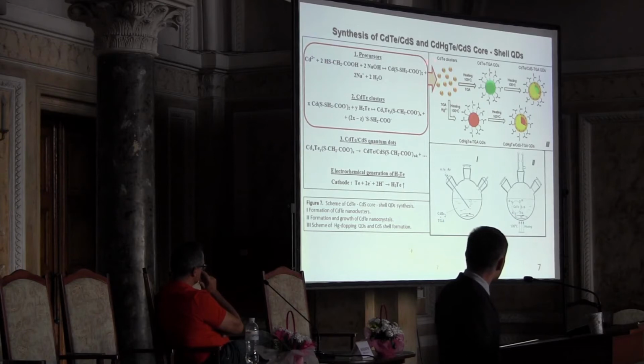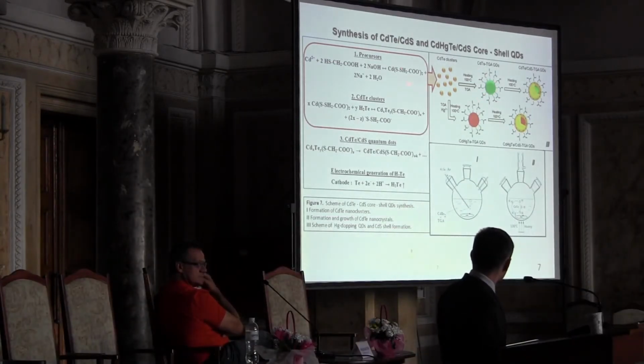And afterwards you get those clusters, and to grow particles out of them, you heat it up, either for short terms, then you get pure cadmium telluride particles. If you do it longer, then partially those thiols start to decompose, and you can basically end up with a core-shell system having cadmium telluride inside and cadmium sulfide outside.